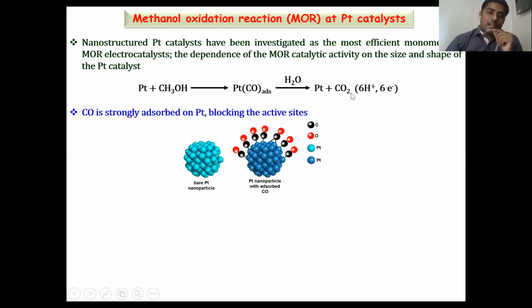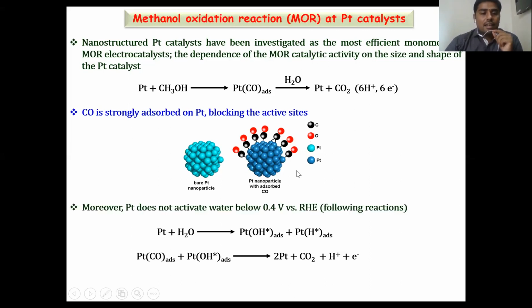In the methanol oxidation reaction, CO is the main intermediate, which strongly adsorbs on the platinum, blocking the active sites of the platinum catalyst. Hence, platinum poisoning can be observed on the platinum catalyst. Moreover, platinum does not activate water below 0.4 volt. So if we want to control the platinum poisoning, platinum-OH bond formation is essential. In the case of platinum, the activation potential is high, and it does not activate water below 0.4 volt.